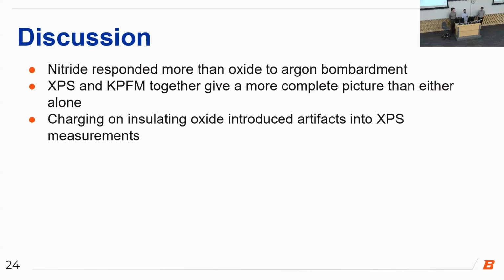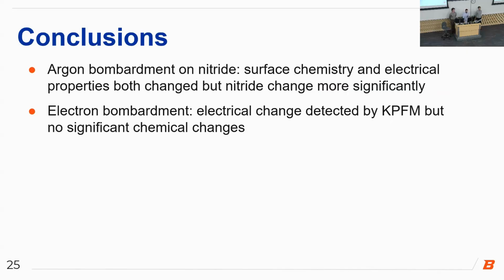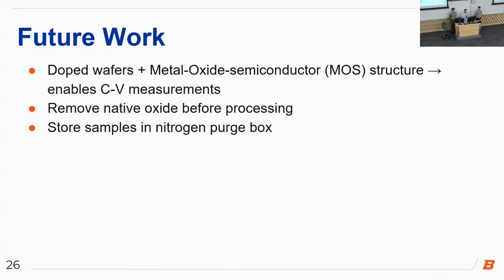Second, one challenge we faced was that our samples are insulating, which caused charge to build up on the surface during XPS measurements, and this introduced artifacts into some of our results and made them harder to interpret. And to conclude, this project showed that manufacturing-related surface treatments do change the charge trapping behavior of the films used in 3D NAND memory. And silicon nitride and silicon oxide did not respond the same way. And argon and electron bombardment did not affect them the same way either.